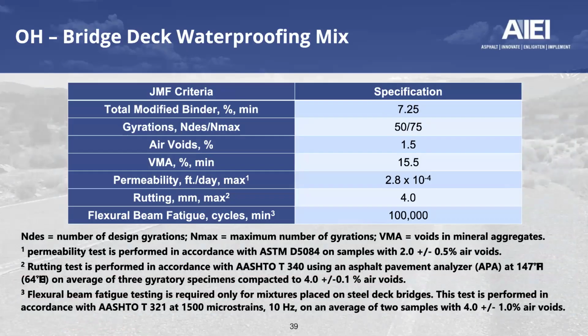In terms of the job mix criteria in Ohio, they are also having a minimum binder content, also very high, in their case of 7.25%. Gyrations are at design, again, at 50 with an Nmax of 75. The design air voids is 1.5%. The VMA on their mixes is 15.5.